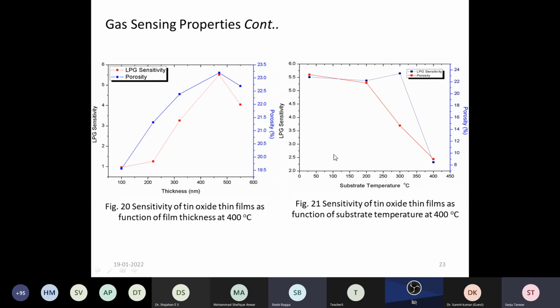And if we correlate porosity with LPG sensitivity, here we can see the film is well behaved with the porosity. It depends purely on the porosity as compared to the other parameters. While for the films deposited at different substrate temperatures, as the substrate temperature increases, the porosity decreases, and at the same time the LPG sensitivity also decreases.